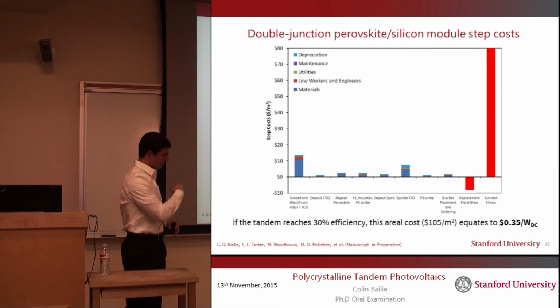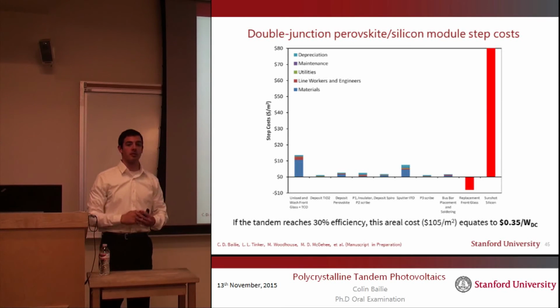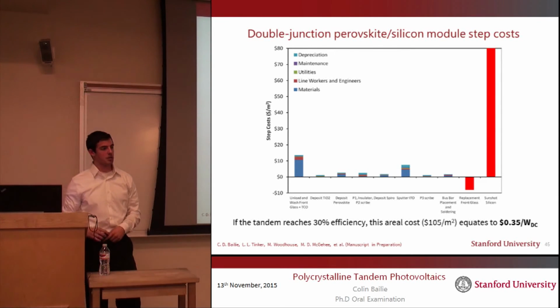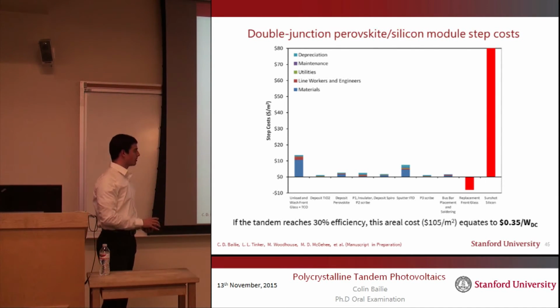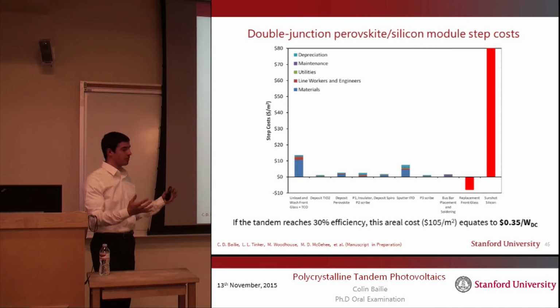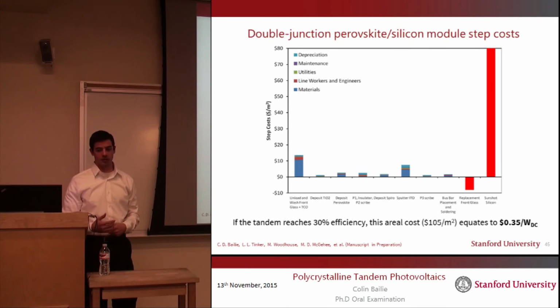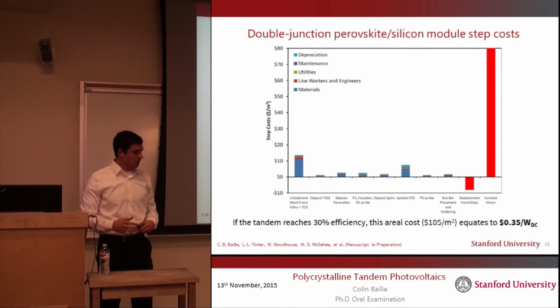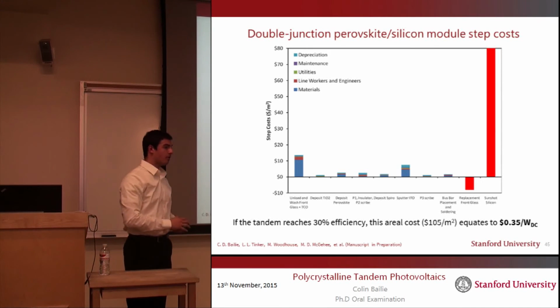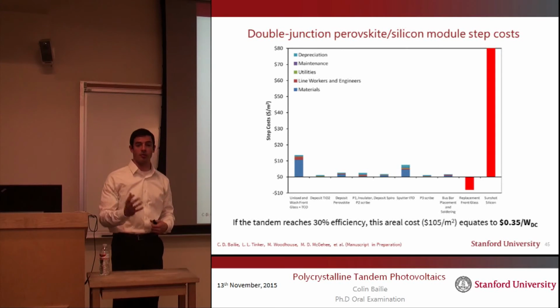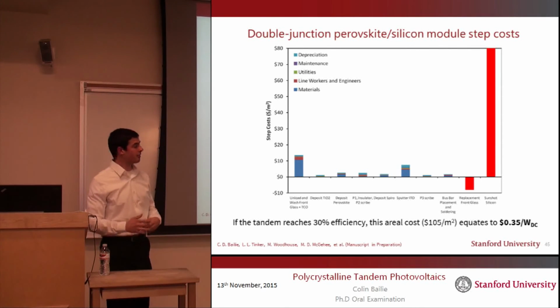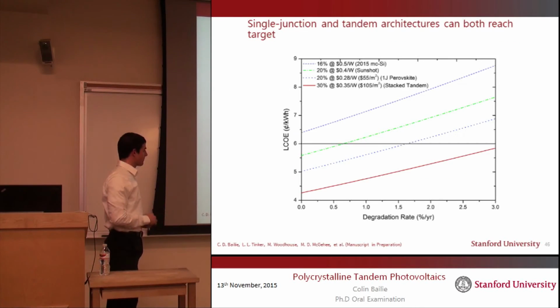And if we take off that front glass sheet and we instead put on our perovskite coated front glass sheet, then we make a module that's about $105 per meter squared, and at 30% efficiency would cost 35 cents per watt. Now, of course, this is a bit more than the 28 cents per watt for the perovskite by itself, but that's not the whole story.